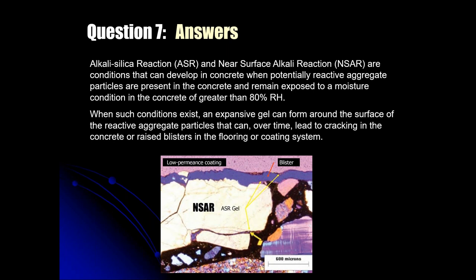Again, it's a very slow process, usually takes 5 to 10 years to even begin to be seen, whereas NSAR occurs much more quickly. Why? Because when you cover the floor with a floor covering or low permeance coating and you don't have a protected slab, that condensation plane, if you will, develops right below the floor covering and coating and puts those potentially reactive aggregate particles into that caustic high pH solution much quicker than it would throughout the body of the slab.